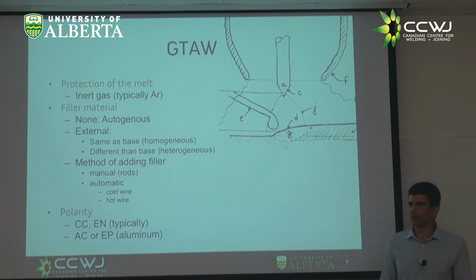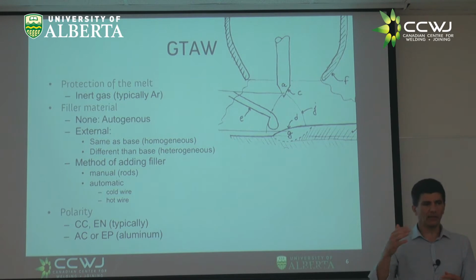In constant current, the intensity of the arc, right? Remember that I mentioned the arc is very hot and also generates a jet that is about the same speed as a jet plane, right? This jet is about the same intensity if it is constant current. So you can be a little bit closer, a little bit farther from the weld, and you always have the same jet, right?